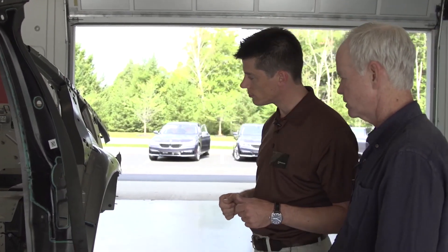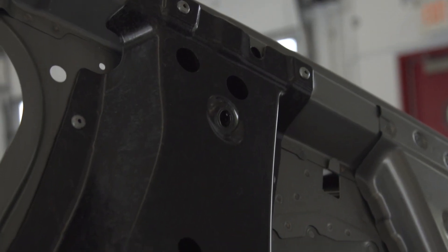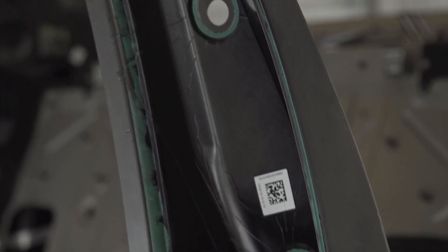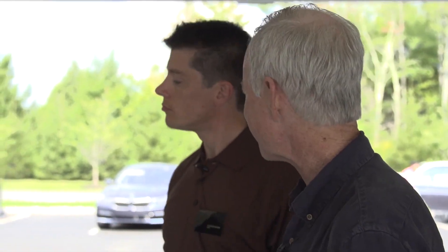Explain this one last little piece here too, because this doesn't have quite the weave in it that these other ones did. This is a reinforcement element for the C-pillar and it's basically made from the recycling material which is left over. You see some of these cutouts here and even on the element on the tunnel. What do we do with that material? So we thought it can be used — the material is cut into like 10-mil pieces and then brought into a plastic casting process which is very familiar with every regular plastic part. So you sweep up all the scrap after you make these pieces and you make that piece out of it. Exactly.